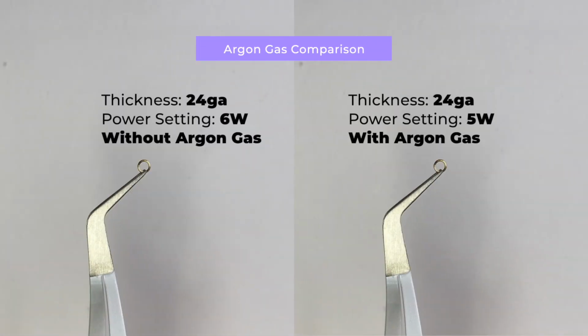For example, for 26 gauge sterling silver without argon gas, I found that you need to weld at 4 to 5 watts to be consistently secure. Whereas with argon, you could weld securely at 3.5 to 4 watts. It's a matter of preference and convenience, whether or not to use argon gas when welding. I'm going to film an updated review on that a little later.